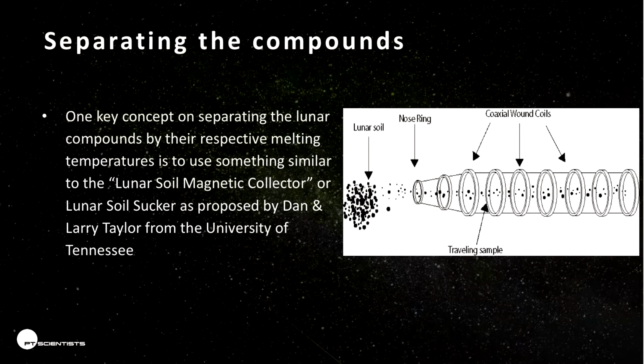But how do you actually separate the materials that you want to use for printing? Not all of the material is printable or is ready for sintering, and so you want to collect material that is small, that is at best fine powdered, which you have plenty, but the size of the particles is very oddly shaped. So it's a little bit difficult to collect the material and to process it so that it can be used for laser 3D printing. And this is where this sucker comes in.